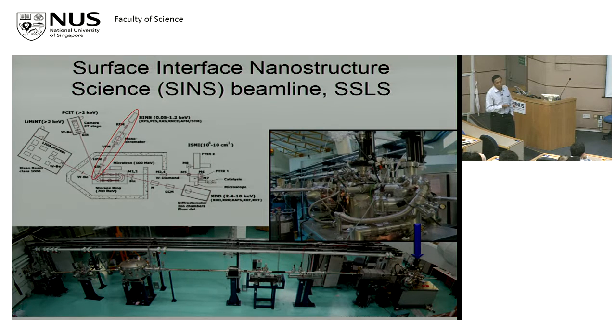Okay, of course, besides the STM, we have other techniques. For example, the synchrotron, we have a beamline. We do a lot of spectroscopies there. We have X-rays in this energy range. Why this energy range? Because we produce low-energy photoelectrons, and photoelectrons of a few hundred electron volts have a very low inelastic mean free path in solids. In other words, they are very surface sensitive. In other words, they only travel a short distance before being scattered, so most of what you measure comes just from the first few layers of the surface.